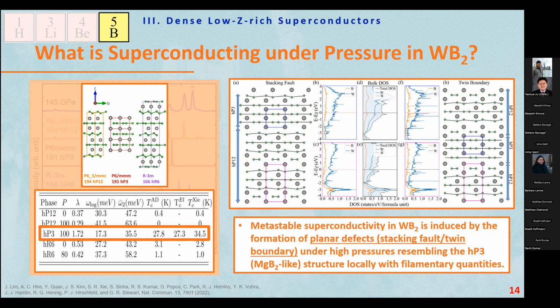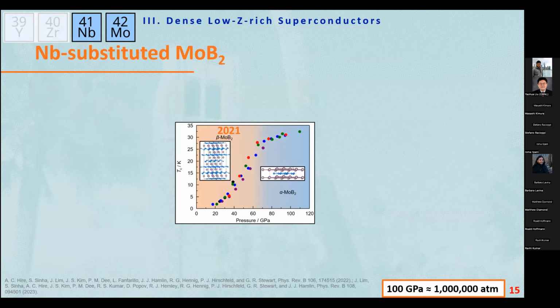That's our answer. And then we have the follow-up. We are still doing the follow-up study to prove this conjecture. And another study we did with the diboride is molybdenum diboride with other substitutions like niobium. Niobium is a good candidate for a substitution study because it is next to molybdenum, and also niobium boride has the MgB2-like structure, with a flat layer of boron. So our hope was that when you put niobium in the molybdenum diboride, it may stabilize the MgB2-like structure. So pure molybdenum diboride at ambient pressure is this buckled structure.